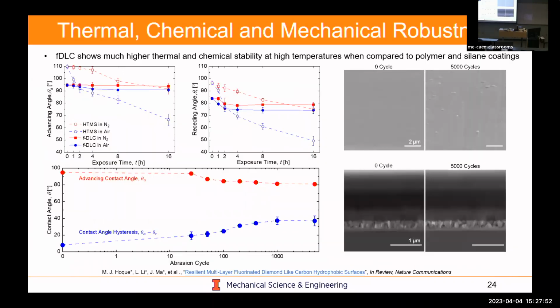If you look at things like effective exposure time to air and to nitrogen environments, you can see that the DLC, which is basically these solid curves, compared to the self-assembled monolayer, which is the dotted curves, the DLC shows much greater stability. So it's got high temperature stability. And then if you look at the contact angle as a function of abrasion cycle, this is mechanical abrasion in a Taber tester. You could go up to essentially 5,000 abrasion cycles. You don't necessarily even notice a difference in the top layer. You do have some increase in the contact angle hysteresis, but you still see dropwise condensation even at 5,000 abrasion cycles.